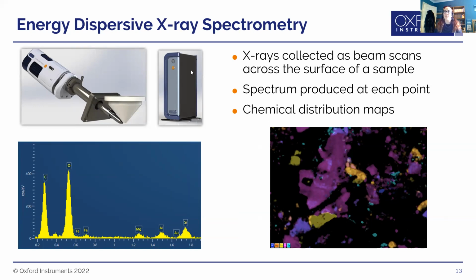The signal that is generated goes to a processor, and that processor then counts and measures the X-ray energies, and it produces a spectrum like this. Along the bottom, we have the X-ray energy, and where we've got a peak, this is where we have an accumulation of X-rays at that particular energy. And because we know what the energy should be for different elements, we can then label it, as you can see here. Now, this spectrum is produced at every position the beam is as it scans across the sample. So we can then produce an elemental map and look at the chemical distribution across that entire sample, as you can see here.